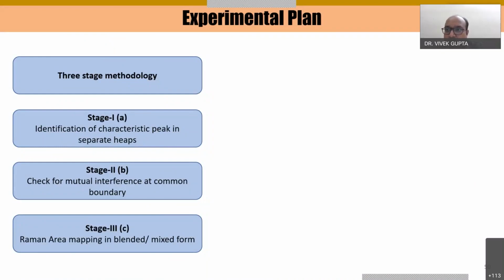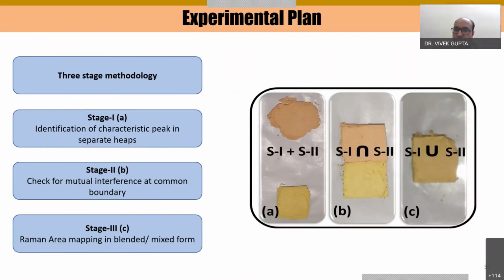We have presented a three-stage methodology which can be used for similar applications. You can also implement this methodology for your respective material. In the first stage, we identify the characteristic peaks in the separate heaps, in the second stage we check the mutual interference at a common boundary, and in the third stage we develop the Raman area map in the mixed form. So these are the three stages. In the first stage we have taken the spectra in isolation, and then we bring them together at a common boundary, so that we can take the spectra of individual materials and check whether the spectra of one material is interfering with the spectra of another or not. And in the third stage we actually blend them together, and we take the spectra of the blended material.